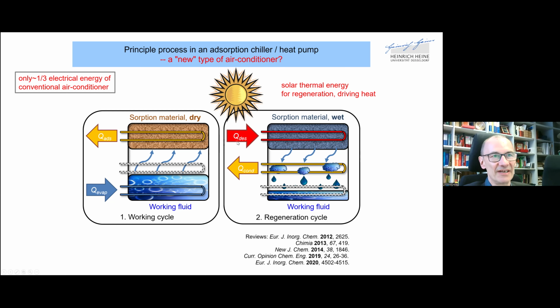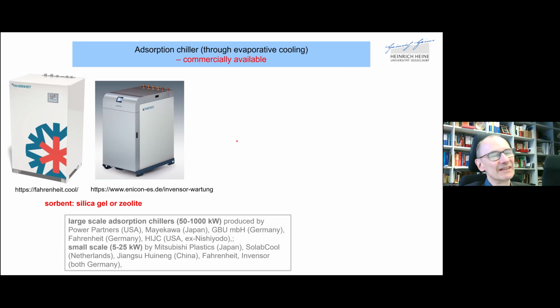So heat is often available, especially if it's below 100 degrees centigrade, which can enter in this process here for the regeneration. So if you now think, that's interesting or fantastic, I can already show you here with these two devices that this process already is commercialized. So the commercialization so far uses silica gel or zeolite, and there are different capacity scales up to even 1,000 kilowatt. And some companies are listed here from USA, Japan, Germany, who manufacture devices like that, which use evaporative cooling or adsorption chilling as a means of generating cold.